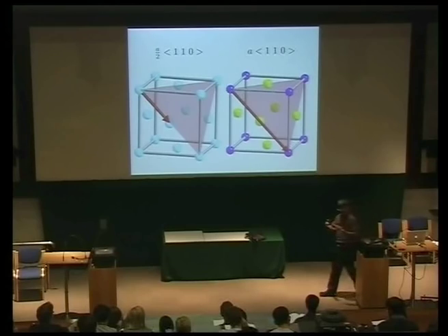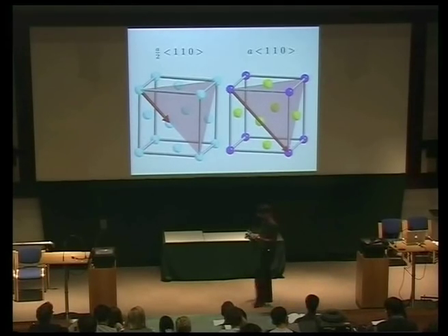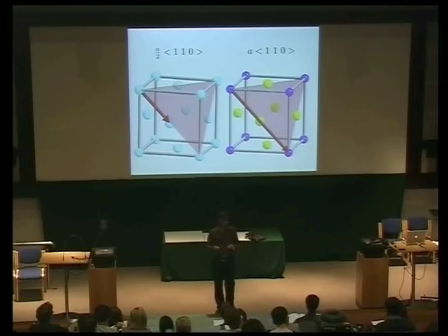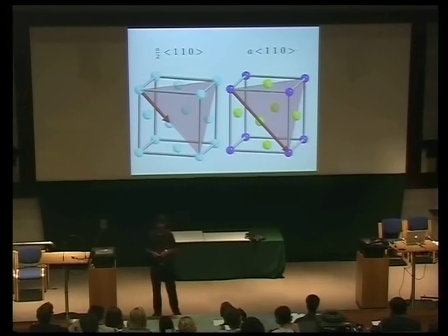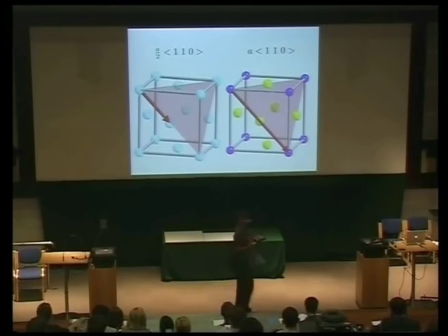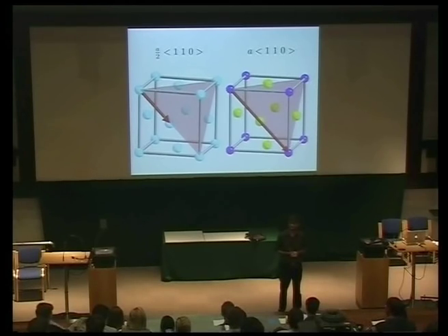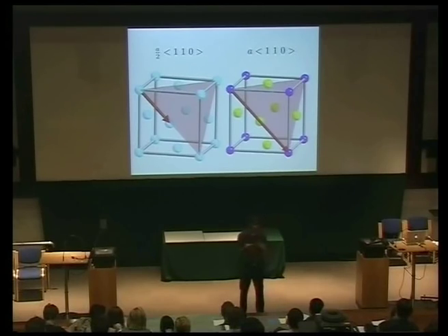Now, if we have coherency, and these precipitates are in cube-cube orientation, that means the lattice planes are continuous across the interface between the gamma and gamma prime, then how do we get strengthening? Because we've tried to get the lattice parameters nearly the same, so coherency strains will be minimal. I mean, haven't we lost the advantage of strengthening using precipitates by making them fit so well? Well, the mechanism of strengthening here is quite different from anything you've done before, and it's as follows.